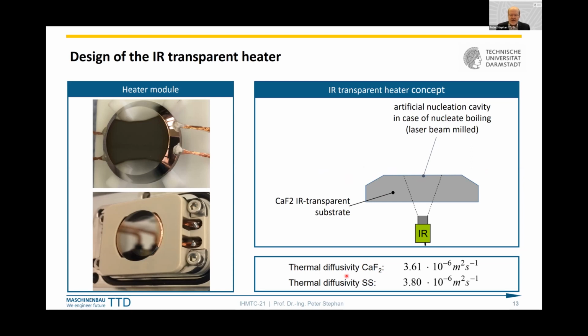The interesting thing is that this calcium fluoride glass has very similar thermal diffusivity as, for example, stainless steel, so the thermal behavior of this infrared transparent glass is very similar to that of stainless steel.